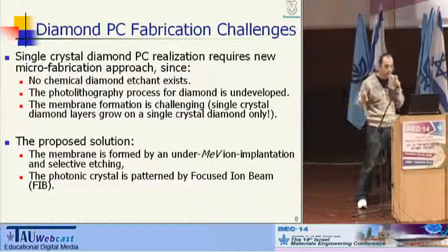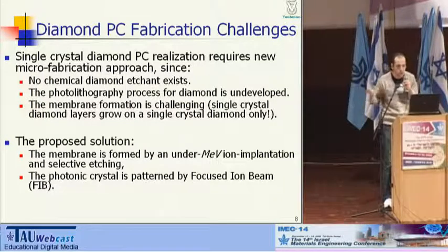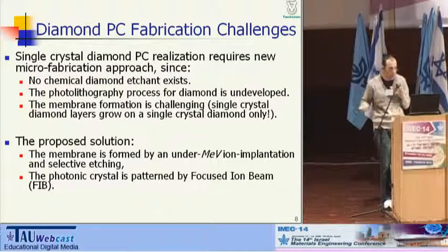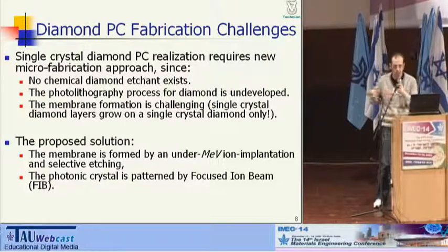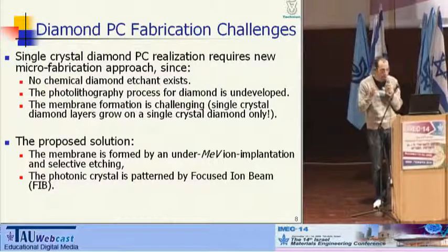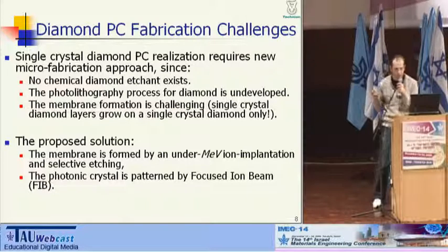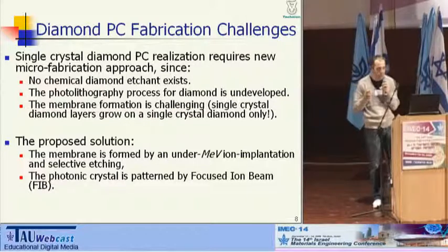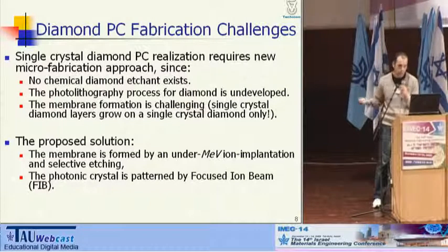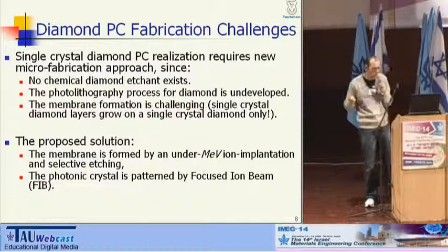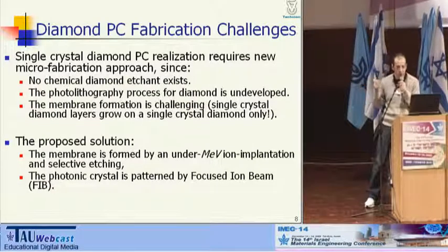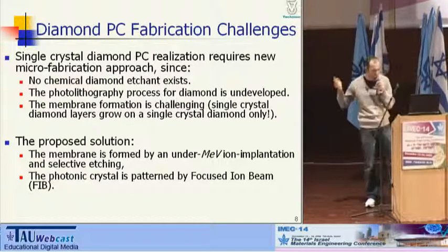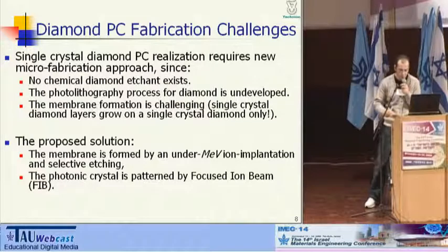Single crystal diamond photonic crystal realization requires new microfabrication technology, since first, no chemical diamond etchant exists. No photolithography process for diamond is developed. The membrane formation is very challenging. And we have proposed a solution where the membrane is formed by sub-mega electron volt ion implantation and selective etching. The photonic crystal is patterned by focused ion beam.